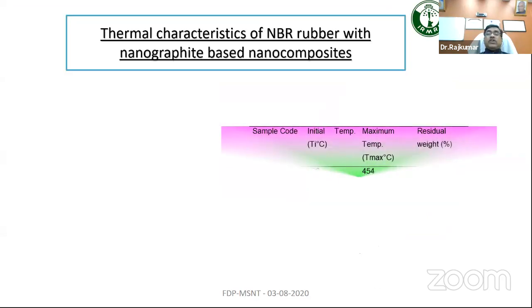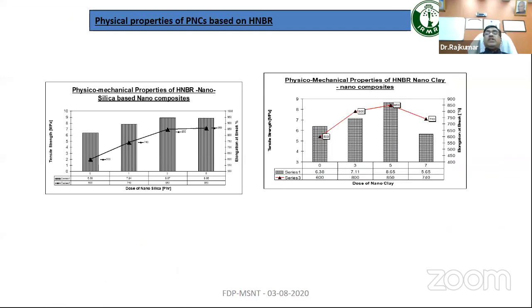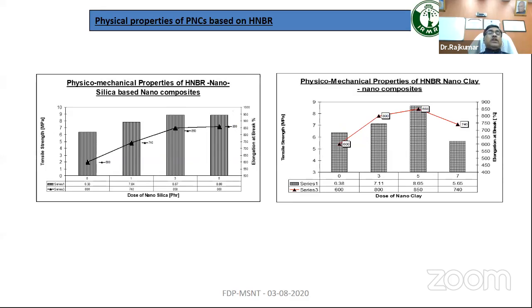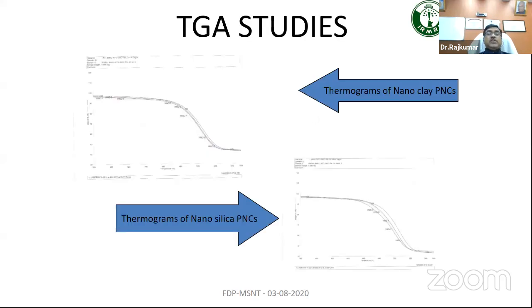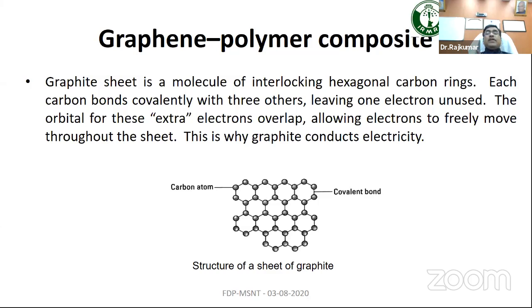At the same time, nanographite also we tried. Basically the thermal stability is increasing, mechanical strength is improving, and barrier properties are reducing. So all such things we have done, including tear resistance improving and mechanical properties improving. When we do TG analysis, the thermal stability is increasing with the PHR. That shows it is proved even at the laboratory level, but when it goes to a higher level, of course the material's characteristics will not change. Only fixing the morphology is the most important.